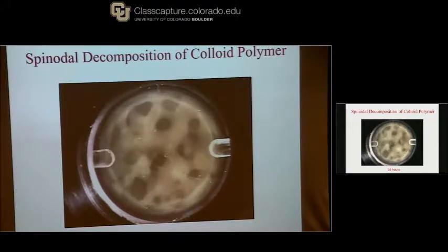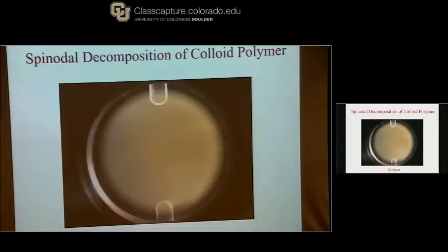And you see you get perfect spinodal decomposition, right? And perfect coarsening. You can see all kinds of cool things. Notice that around the edge there are always particles. What does that say? Particles wet the side. They don't wet the surface, because you can see through it, but they wet the side, which was made of a different material. I'll play it again. This is really just looking at spinodal decomposition.